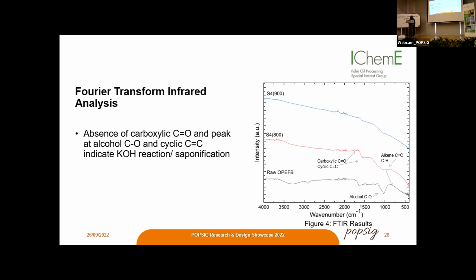When you compare raw OPEFB and the synthesized carbon samples, it can be seen that the carboxylic C=O peak is absent and the peaks at alcohol C-O and C=C drop, which indicated that the KOH reaction takes place. But when you compare 800 degrees and 900 degrees, 900 degrees has insignificant peaks, which may be due to the increase in bond breaking and the removal of elemental content.